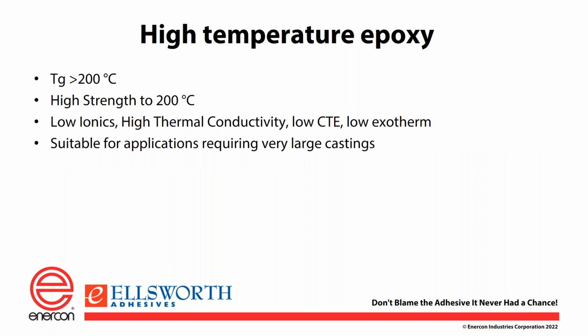Next slide, please. High temperature epoxies. This is a blast from the past in the sense that when I first got into this business, there was a lot of people that needed high temperature epoxies, mostly because people weren't particularly good at thermal management. But today, that's not a very common thing, and yet we have been asked to make a product that is very high in temperature capabilities with a TG in excess of 200 degrees C. It maintains great compression and bond strengths up to 200 degrees C, low ionics, high thermal conductivity, low coefficient of thermal expansion, and suitable for very large castings because at very low exotherm, it's a slow reaction. But it's only unique because of the fact that it's just not done that often these days.